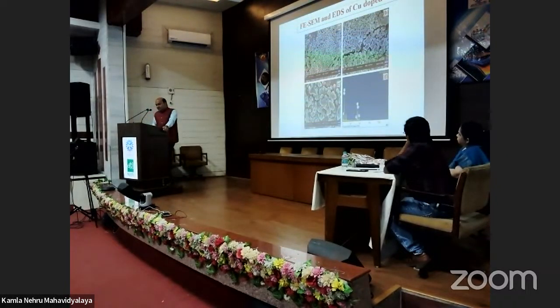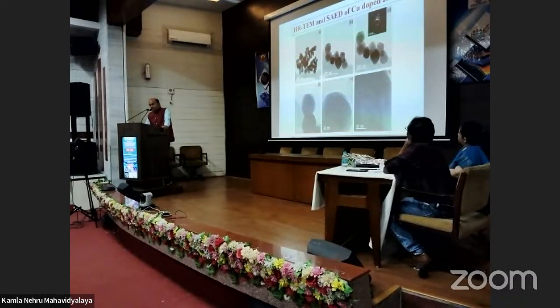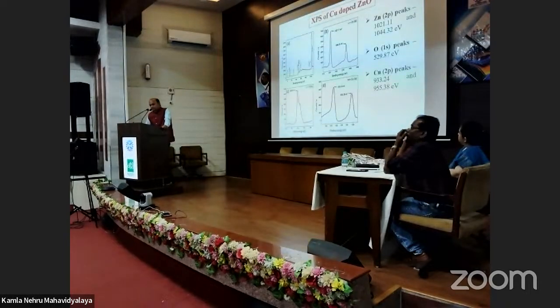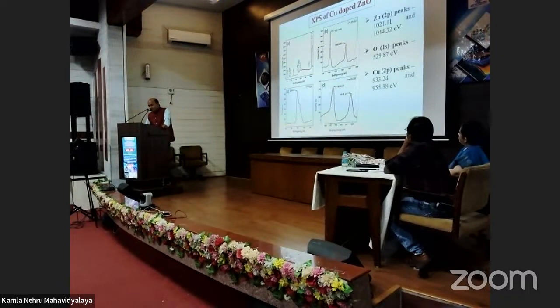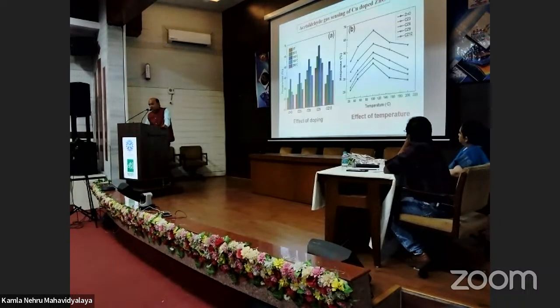This is the morphology study. A uniform and dispersed form of the material is observed, with uniform size. This is the HRTEM. This is the XPS of copper doped zinc oxide. Zinc 2p shows binding energy from 1021.11 and 1044.32 electron volt. Oxygen 1s is fixed at 529.87 electron volt, while for copper 2p it is 933.24 to 955.38 electron volt.